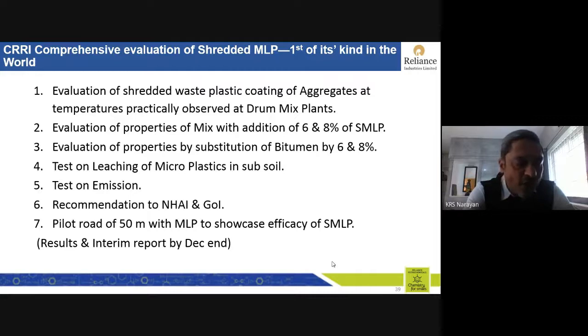We wanted to find out the temperature at which the drum mix plant operates. This is a practical solution which we want to offer. So we wanted to see at what temperatures the multi-layered plastics were melting, as simulated at the drum mix plants. So we tried to simulate one inside the CRRI itself. We are working on that. Evaluation of properties of mix with addition of 6 and 8% of shredded multi-layer plastic. We are also evaluating the properties by substitution of bitumen by 6 and 8%.